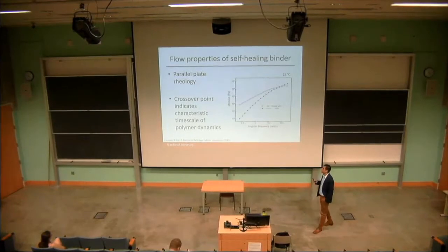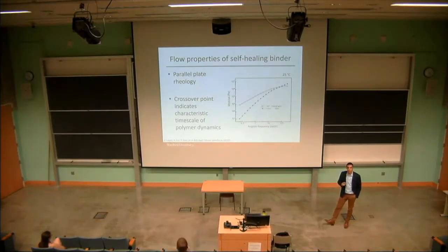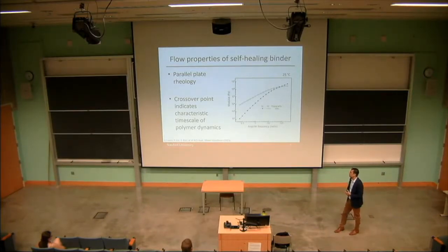To probe the mechanics and really quantify what we were doing by changing these crosslinker amounts, we turn to rheology. And so if you're not familiar, you just stick the material between two plates and you oscillate one of the plates while you measure the stress or the strain, depending on what you're pushing. And the plots end up looking like this, so you can use different frequencies of that oscillation at small strain. And the open squares here are the loss modulus, that's the liquid-like properties of the material, whereas the closed circles are the storage modulus or the solid-like properties of the material. So you can see at low frequencies or slow times, we're actually getting a material that behaves like a liquid, so it's flowing. And we see that because we have the loss modulus dominating over the storage modulus.